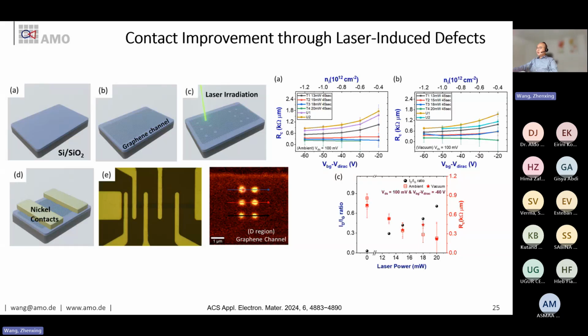Then you can see clearly this is, I think, the D peak of the graphene here. Then you can see this area which is exposed with laser has a very high D peak, which means they're basically defective. Then you can make contact on top of it. Then you can also do TLM and so on. We can also achieve very nice contact resistance.